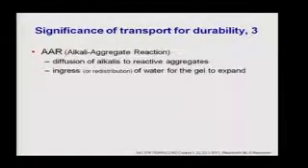Another example of deterioration is alkali aggregate reactions, where reactive aggregates react with the alkalis in the binder. We have a very high pH in concrete — it could be up to 14, usually above 13.5 — and some aggregates are not inert enough to resist that. They can react with the alkalis forming a gel that will absorb water. This means you need a couple of transport processes: the alkalis must move to the aggregate, which requires a certain humidity in the pore system. And once you have the gel as reaction product, you need water to get it to expand, which also takes time and significant humidity.